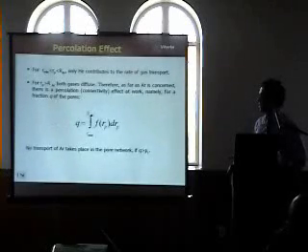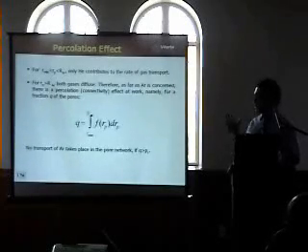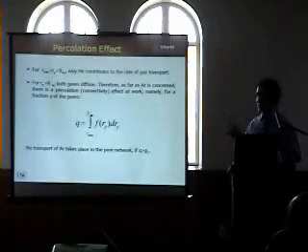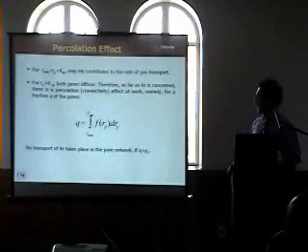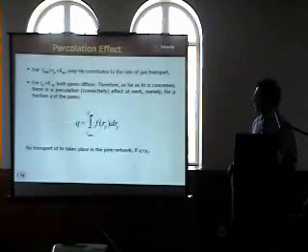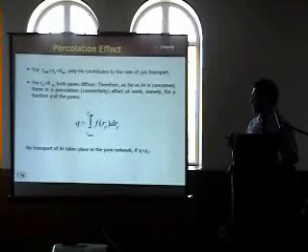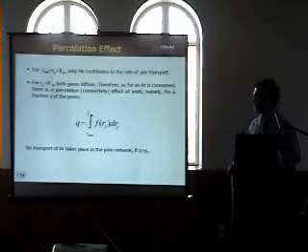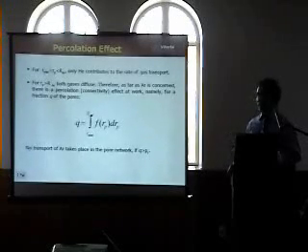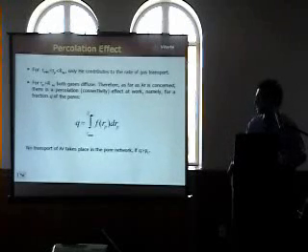and we can define the percolation effect as Q. That means it is the percentage of the pores that are inaccessible to argon, and just helium can diffuse through them. And if this Q, which is a function of pore size distribution, is larger than the percolation threshold, which is again a function of connectivity, then no argon will diffuse through our system.